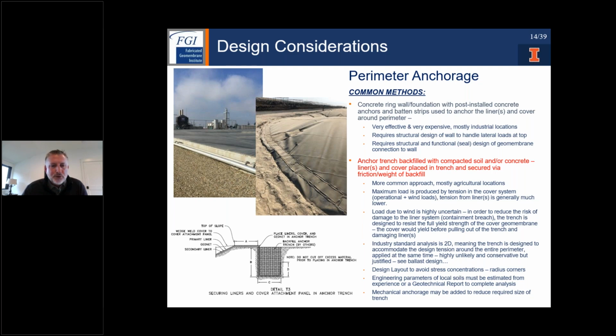The main thing you want to do in the layout of the system, at least for the anchor trenches, is avoid stress concentrations, meaning you want to radius the corners. You don't want hard 90-degree or angled corners that will concentrate stress and tend to concentrate more force in that area of the liner anchor trench system, so that you don't pull the liner and cover system out. Mechanical anchorage such as earth anchors or helical anchors can be added to the bottom. If you have to limit the size of the anchorage trench, or if you have very high tensions, that can easily be done as well.